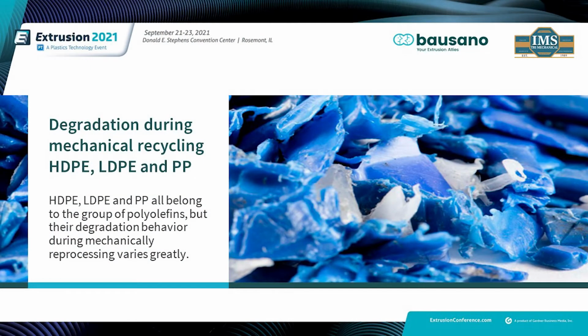For example, in 100 consecutive extrusion cycles or uses, through a twin screw extruder using HDPE, a decrease in melt flow index was observed. Also, an increased extrusion torque and complex viscosity occurred within the first 30 cycles. However, with LDPE, it was observed that for the first 40 cycles, the processability and long-term mechanical properties didn't change.